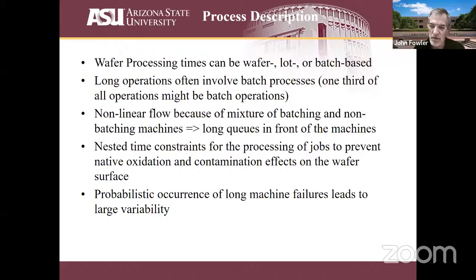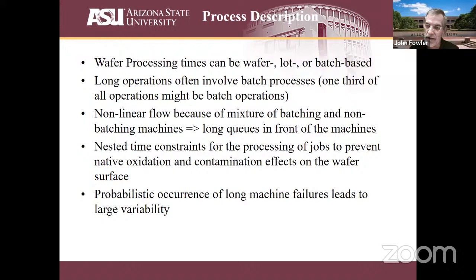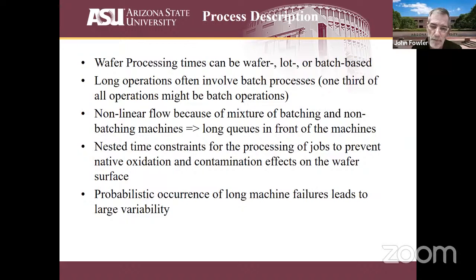There are also nested time constraints that try to prevent native oxidation and contamination effects on the wafer surface — if you exceed those time limits, the product doesn't yield well. Process yield has been the key driver in this industry, even more so than productivity. To get a very small percentage increase in yield they're willing to sacrifice some throughput, though this is starting to change.